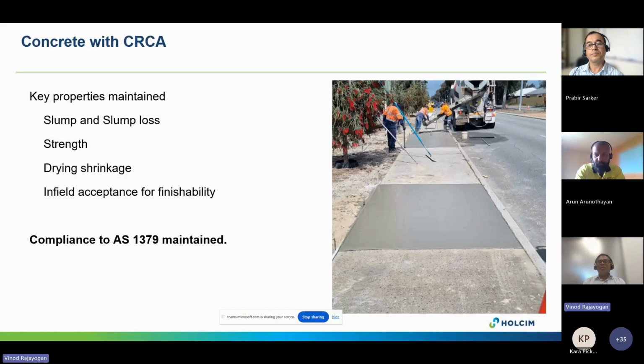While supplying concrete, it is often understood that slump and slump loss are critical. Strength is a concern if people are worried about loss in strength, drying shrinkage and infield finishability. Data has found that over time there has been minimal impact to slump loss, strength, drying shrinkage and infield finishability, provided the recycled content is about 10%.